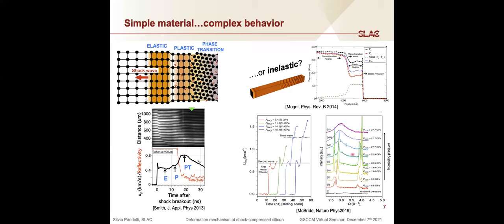recent in situ X-ray diffraction studies that have been able, because of the time delay of the X-ray measurement, to correlate the onset of the different waves, so these three waves, with actually the elastic deformation followed just by the phase transition itself. So this was already suggesting that this deformation mechanism is possible in silicon.